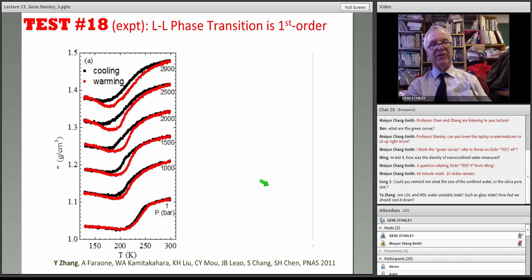So the question that Yang Zhang asked is, I'm supposed to have two forms of liquid water, HDL and LDL. Then I should be able to do the identical experiment and see the identical hysteresis. And that's what you see here. The bottom curve is at 1 bar. There's no hysteresis because we're clearly in the one-phase region. Nothing's happening. At 1,000 bars is a little bit of a difference, hardly outside experimental error. By the time we're up to 1,500 bars, there's a big difference.